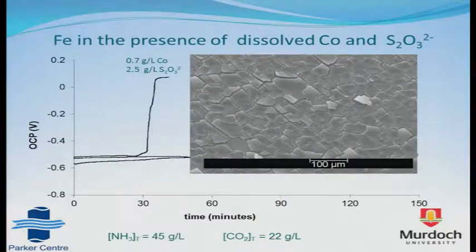On observation of the surface following immersion in both cobalt and thiosulfate solution, you get this surface layer, which is thought to be a cobalt sulfide layer. It's confirmed to be, but I couldn't get a specific stoichiometry or a specific phase because it appears to be amorphous.